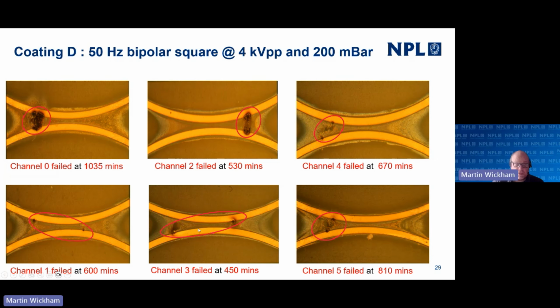But again, you can see that it's not always the areas of highest field strength where we see the failures. It tends to start at the edges, and that's not too surprising when you look at coatings. Generally, their weak link is the edges where they go around corners, and then it tends to perhaps break through one side, and then it looks for the weakest link on the opposite side, and then starts to flash over between those two failure points. That's our hypothesis at the moment.